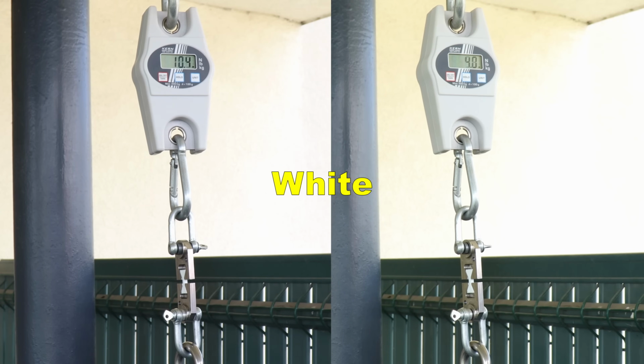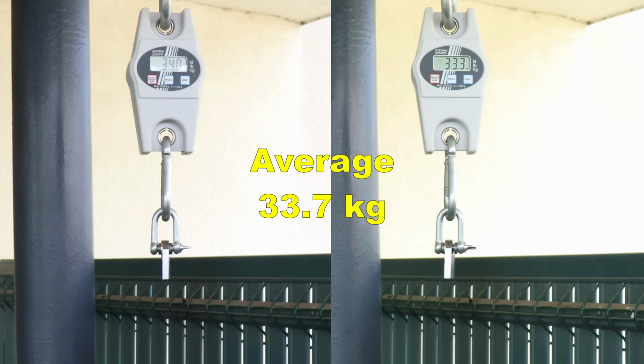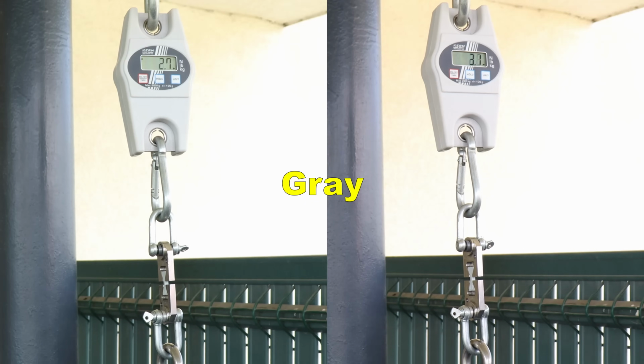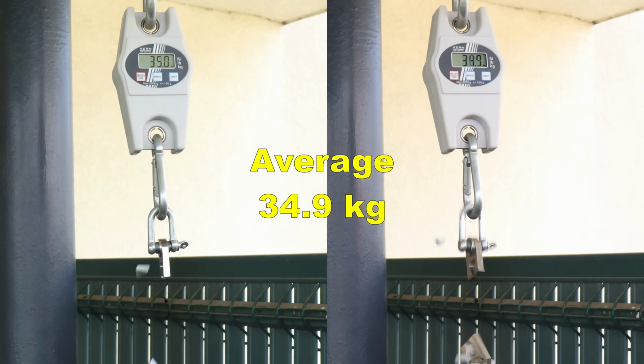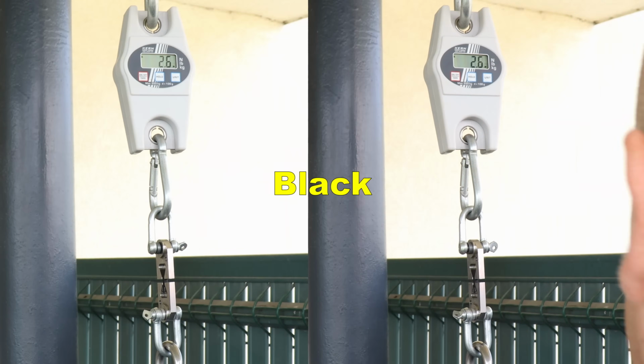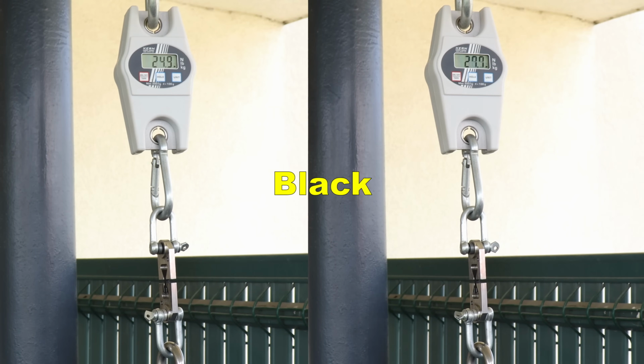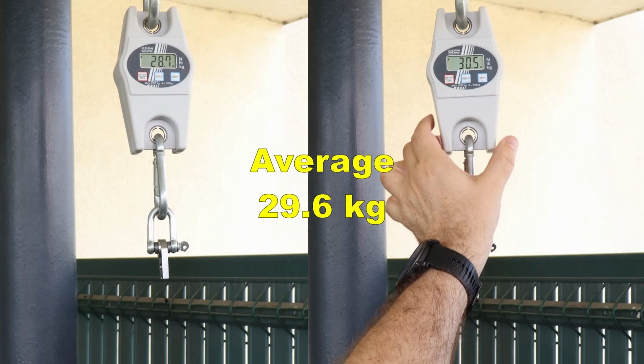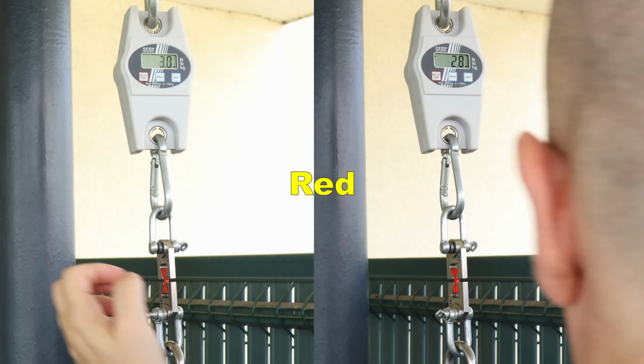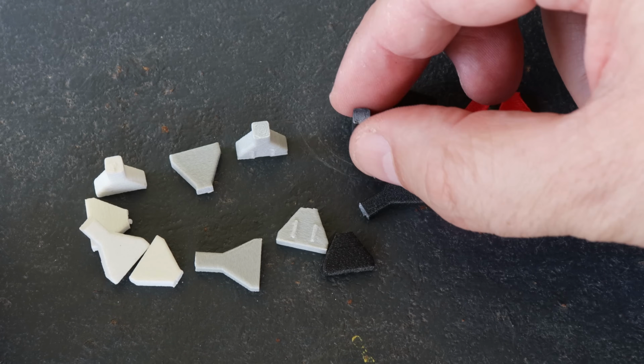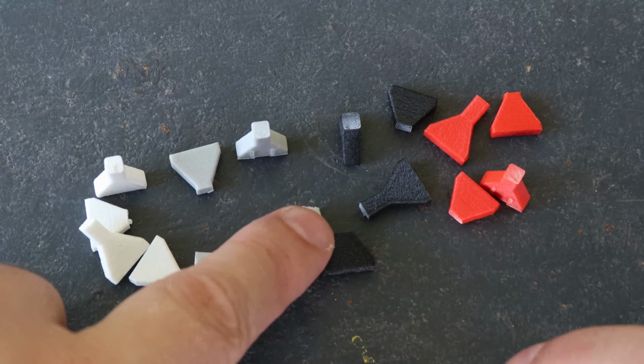Layer adhesion test with vertically printed test objects. White: 34, this is good for the ABS. Gray: 35. Black: 30 kilograms, this one is a little bit weaker. The red: 33. So this time the black was a little bit weaker compared to the other three.